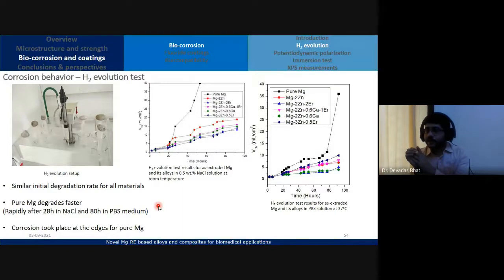And what happens here is that as the test progresses, inside the flask there will be some amount of electrolyte, right? That electrolyte level drops after a period of time. Why does it happen? Because when the level drops in that particular region, hydrogen will occupy it. So when magnesium gets corroded, there will be evolution of hydrogen.